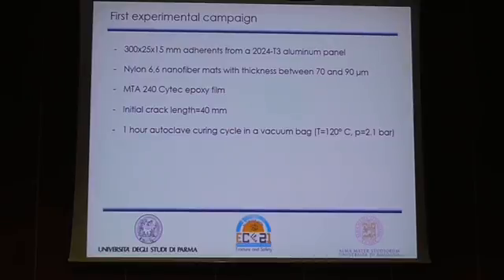2024 T3 aluminum panel was manufactured in order to obtain some 300 times 25 times 15 millimeters adherents. The side of the adherent which was aimed to be bonded was sanded. And two configurations of specimens were considered, the so-called virgin configuration without the reinforcement, and a nanomodified configuration in which a nylon 6.6 nanofiber mat was placed at the interface.